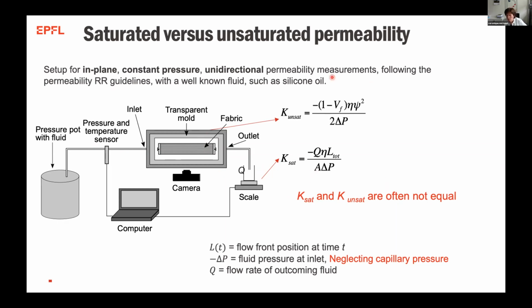So what we observe is that K sat and K unsat most often are not equal, but they should be equal because you measure the permeability of a fabric, and the permeability of a fabric depends only on the fabric. It's a geometrical feature that depends on the volume fraction that you have and on the arrangement of the fibers. It should not depend on the way you measure it. And so what can we do with this? Well, we know that in this measurement here, delta P is wrong. So the K unsat is a K unsat that is measured with the wrong delta P.